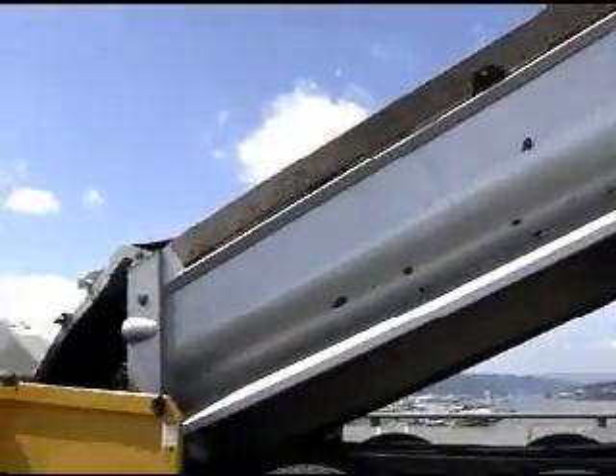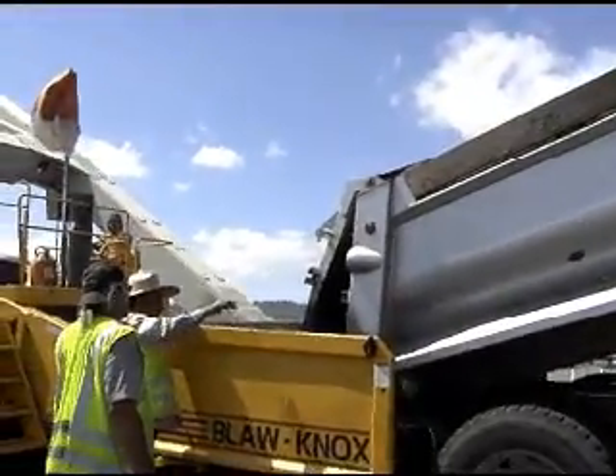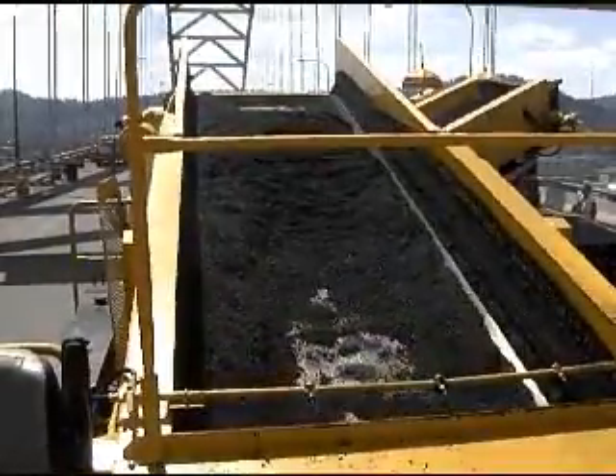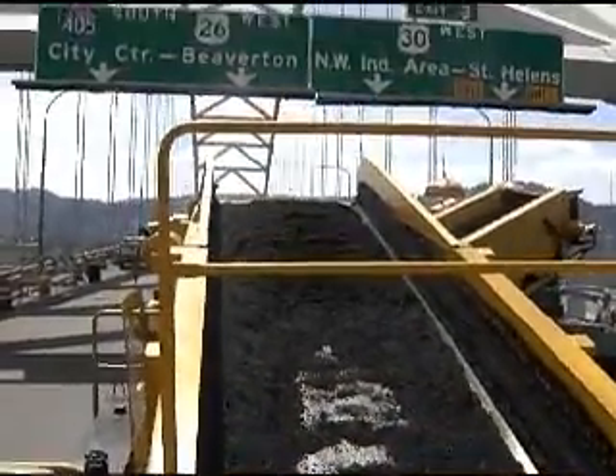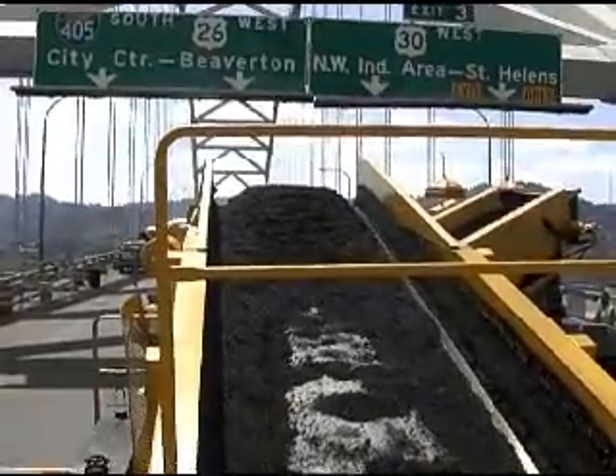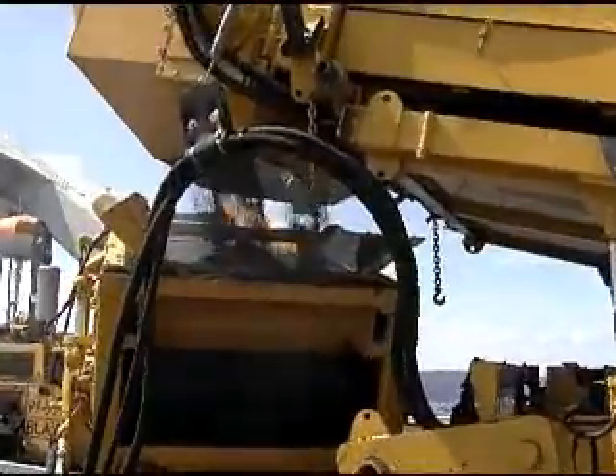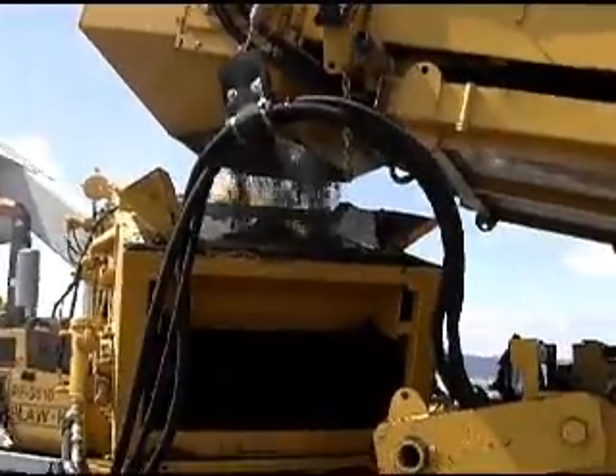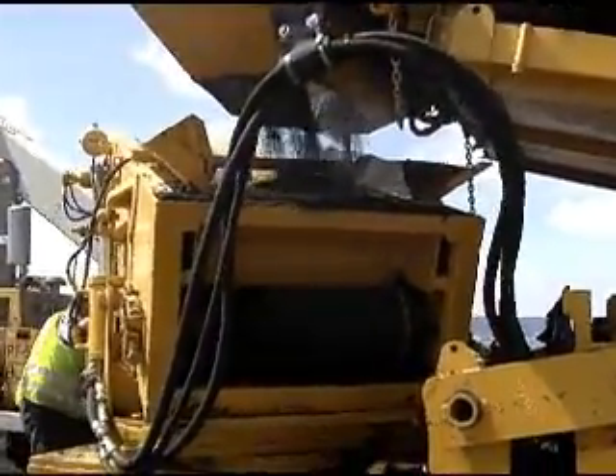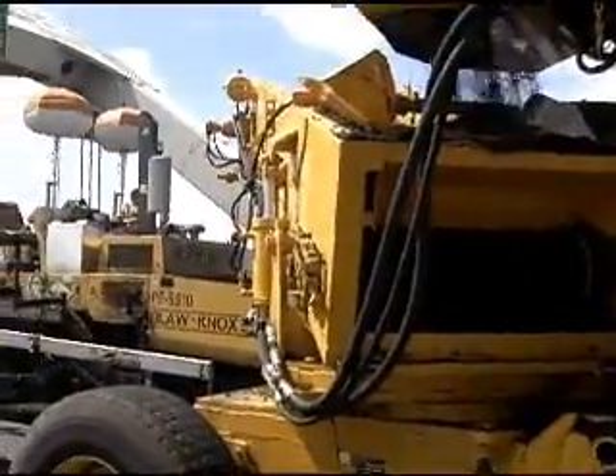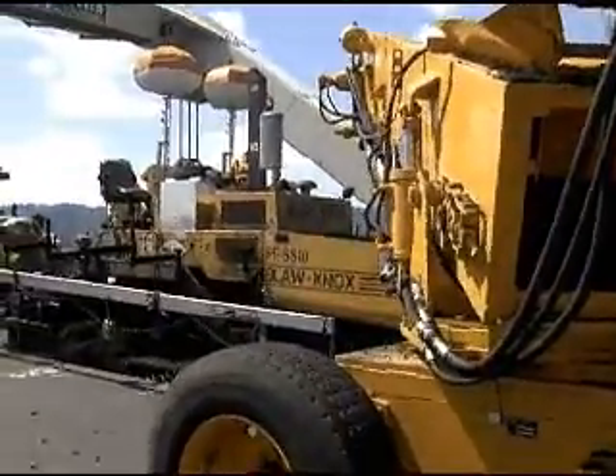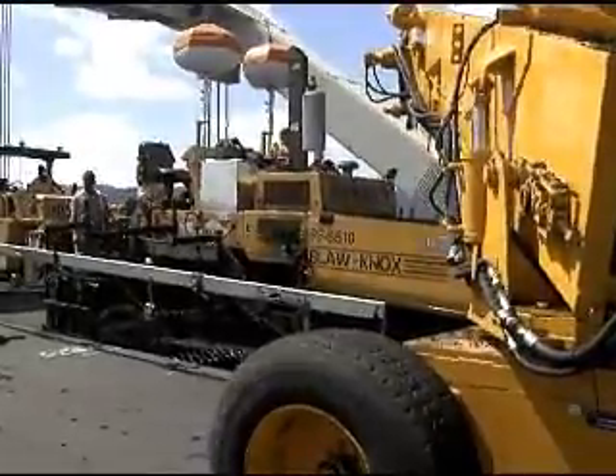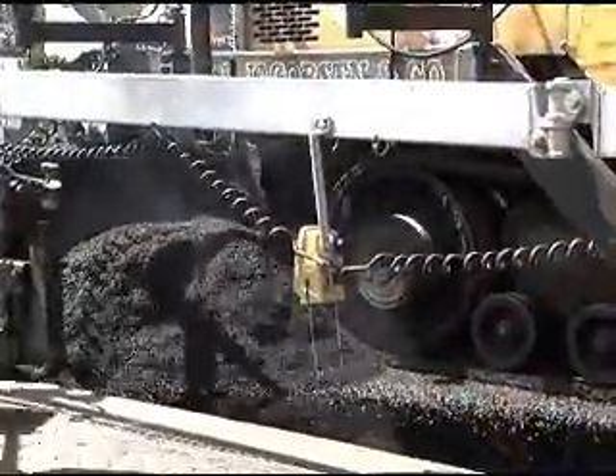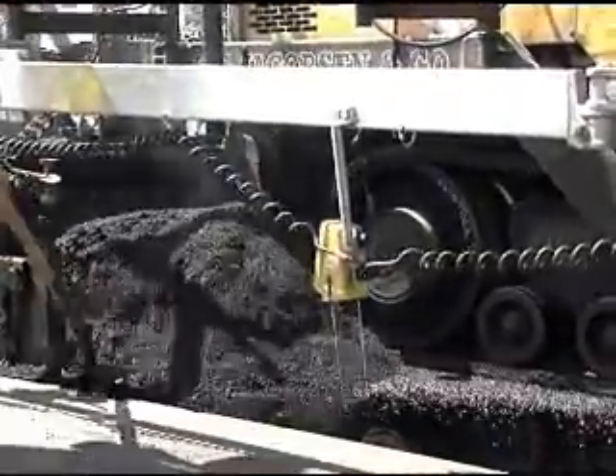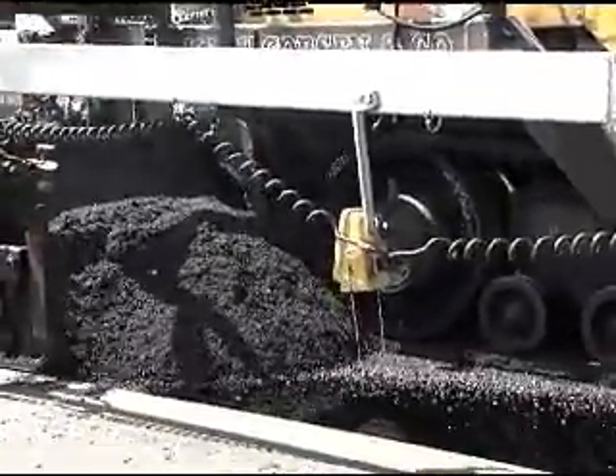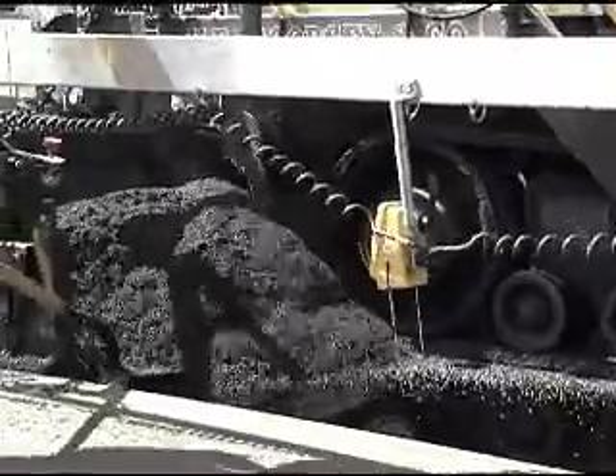So the epoxy asphalt is being produced by a company called KF Jacobson, and their asphalt plant conveniently is located right below the bridge, and so they have a very quick haul to the project from the plant. Even with that, the product is very sensitive to temperature and time requirements. In fact, our specifications have some very rigorous time limits on how much time the asphalt needs to sit in the truck before it's placed, but also it needs to be placed within a certain time frame as well. And it's all dependent on temperature of the mix. If the temperature is a little bit hotter, the contractor has less time to place it.